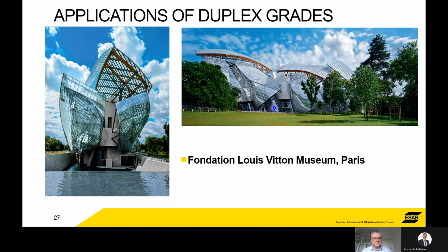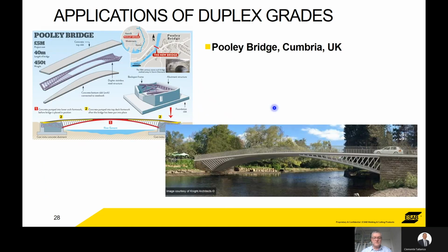And a couple of applications for architectural use. We've got the Louis Vuitton Museum in Paris and also this bridge in the UK, both of which use duplex stainless steel because of the strength. You can reduce the weight. This bridge in particular was able to be lifted in one piece, so it could be assembled off-site and lifted in one piece. Plus, both of these architectural applications don't need painting, they don't need maintenance. So the stainless steel won't rust, won't start looking bad and need painting. So in effect, it's a cost saving too.